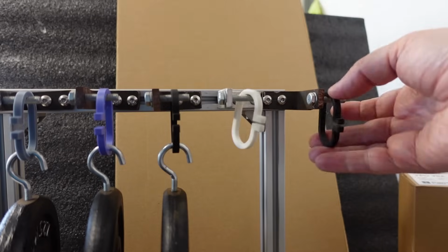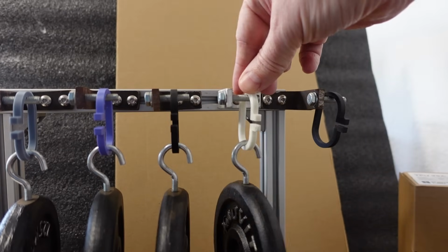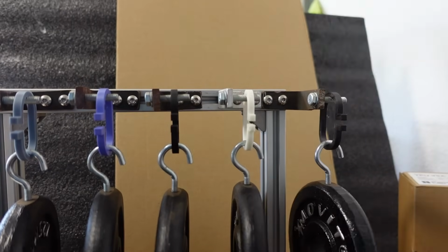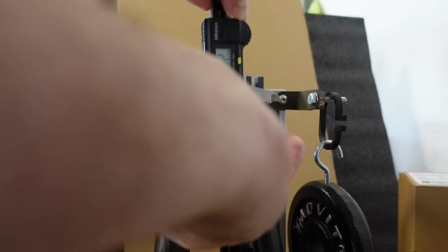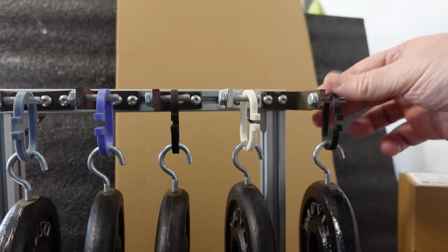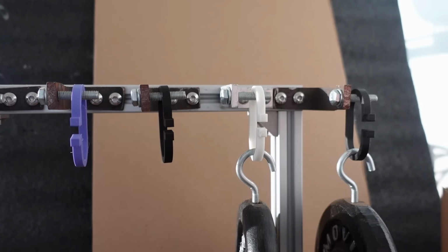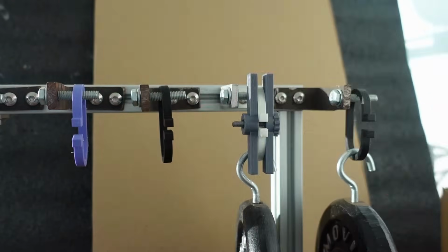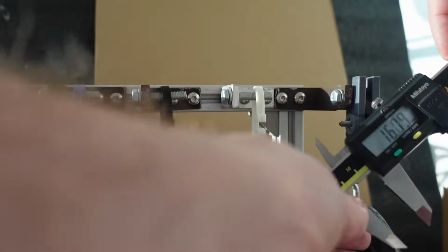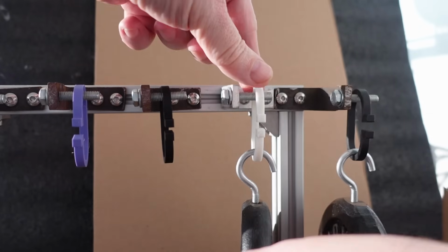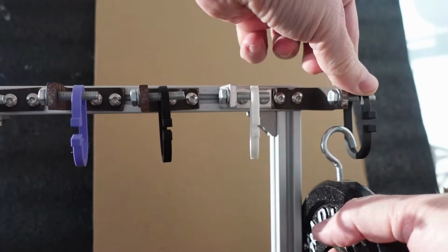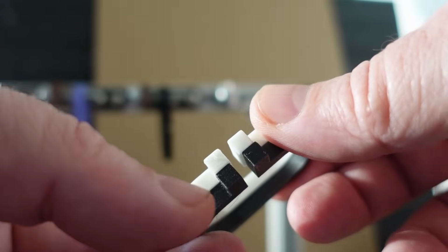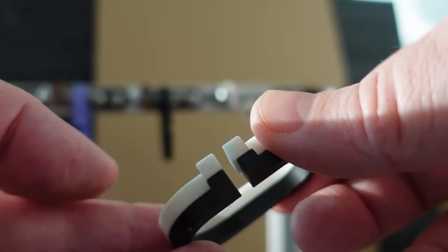The creep test, the deformation under the constant load in the next 5 days, and the load will be 1.25 kilograms. Locking the position for more accurate measuring of the distance between two reference surfaces, and similar values I have in both cases. Day 5, and I think smaller deformation is on the glass fiber version. 1479, 1609. And now let's remove the load. Side by side, minimal, but more deformation on carbon fiber version.